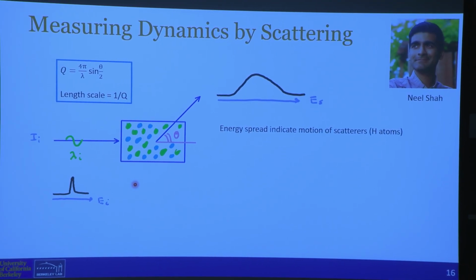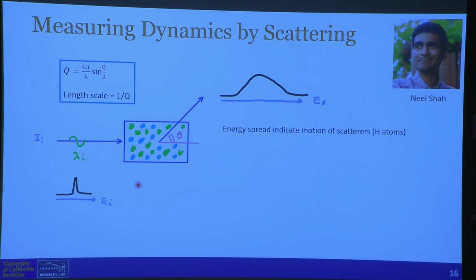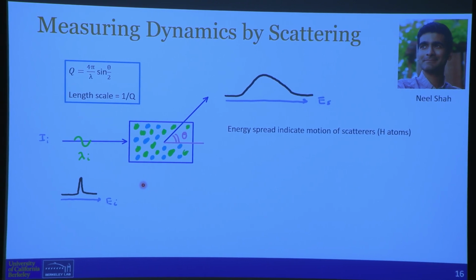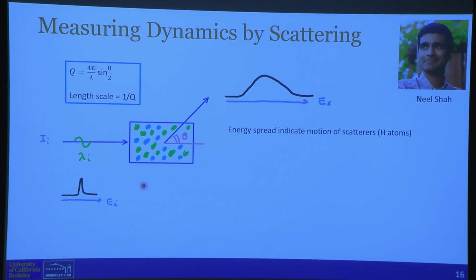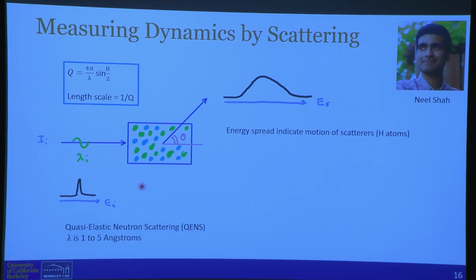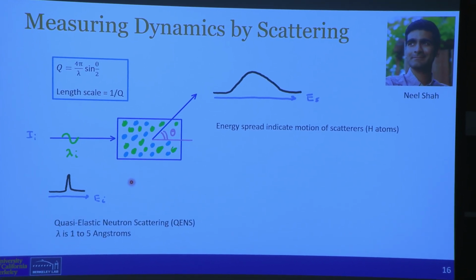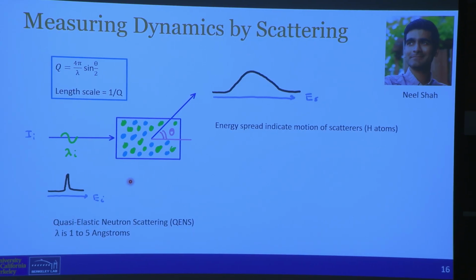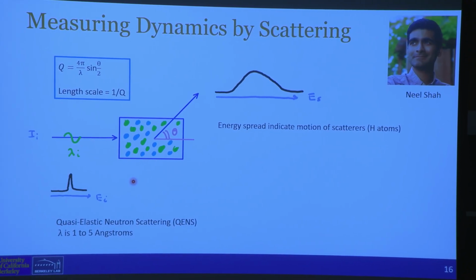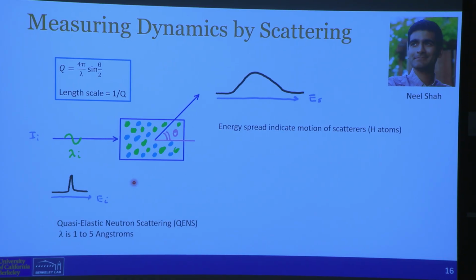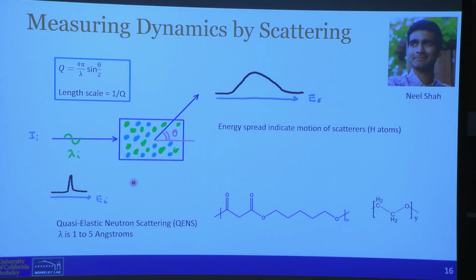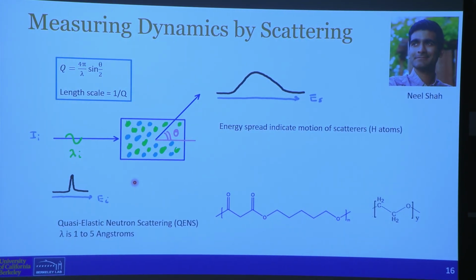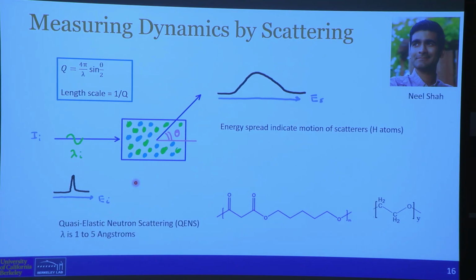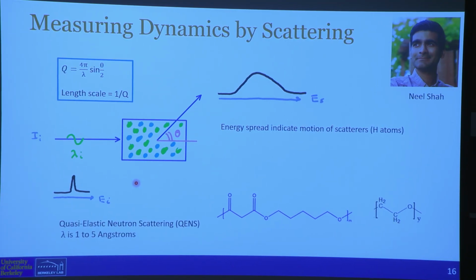And in the case of neutrons, you're only sensitive to the motion of hydrogen, because it turns out to have an incoherent scattering cross-section that's about 100 times everything else. And when you use quasi-elastic neutron scattering, the wavelength is 1 to 5 angstroms, and so the length scale is in that vicinity. Okay? So we are watching dynamics on the angstrom length scale, and our polymers are loaded with hydrogen. So what we are looking at is how our solvent molecules are moving due to the presence of ions that we will add to it.